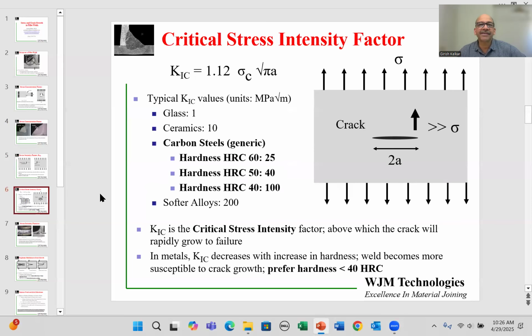Now, the stress intensity factor, there's a critical element to that. So this is called a critical stress intensity factor, K1C. The one over here stands for the fact that we are pulling the two components apart, so in a tensile loading. If the loading on the fillet weld would have been shear, then this would have been K2C, which is a slightly different formula, but similar sense. So the K1C has a constant over here based on the geometry, stress, and a square root of pi, and a is the dimension of the crack. So now in this formula, we have both the stress as well as the size of the flaw.